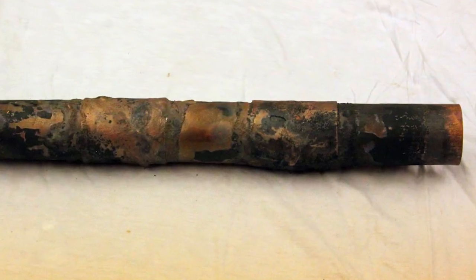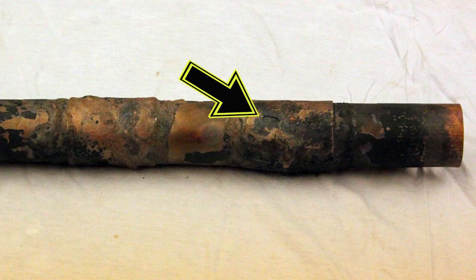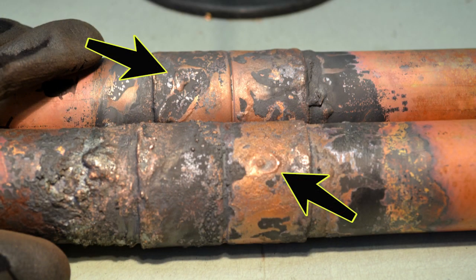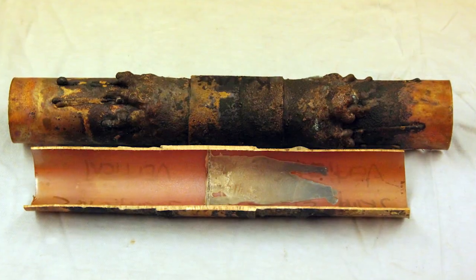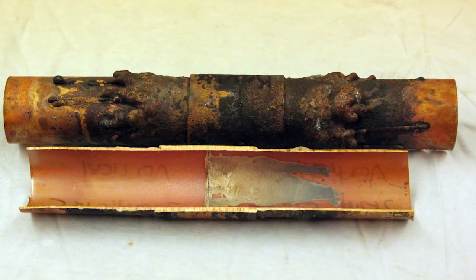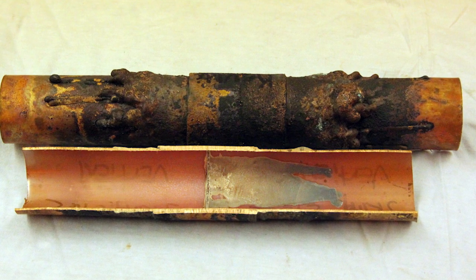NFPA 99 states that any sign of erosion of base metal is unacceptable, and for this test is an automatic fail for that braze position. Be aware of your heat placement at all times. For this test, filler metal in excess on the exterior or the interior can be considered a failure.